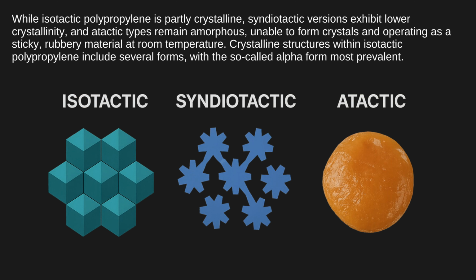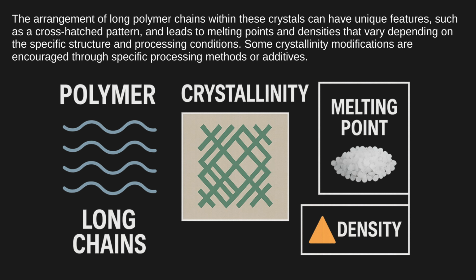While isotactic polypropylene is partly crystalline, syndiotactic versions exhibit lower crystallinity, and atactic types remain amorphous, unable to form crystals and operating as a sticky, rubbery material at room temperature. Crystalline structures within isotactic polypropylene include several forms, with the so-called alpha form most prevalent. The arrangement of long polymer chains within these crystals can have unique features, such as a cross-hatched pattern, and leads to melting points and densities that vary depending on the specific structure and processing conditions. Some crystallinity modifications are encouraged through specific processing methods or additives.